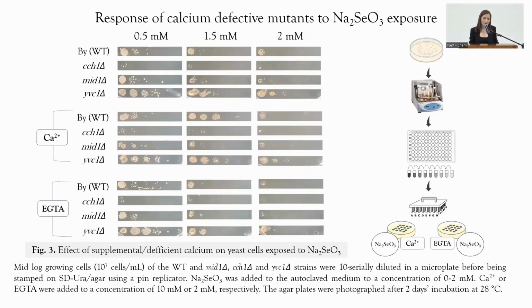To better understand the response of calcium-defective mutants to sodium selenite exposure, we assessed the effect of supplemental and deficient calcium on yeast cells exposed to sodium selenite. Meaning that we again serially diluted the culture of each strain and stamped it on agar media, this time on synthetic defined media enriched with sodium selenite, but also with calcium or EGTA, which is a calcium chelator and therefore creates a medium deficient in calcium.